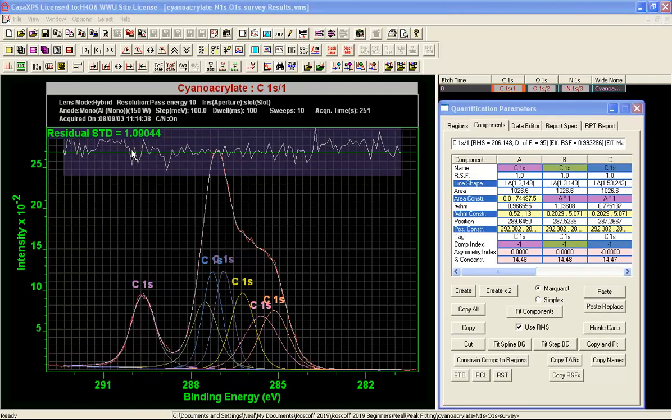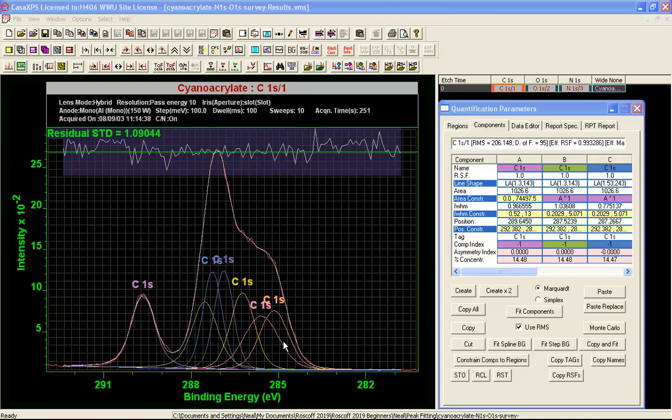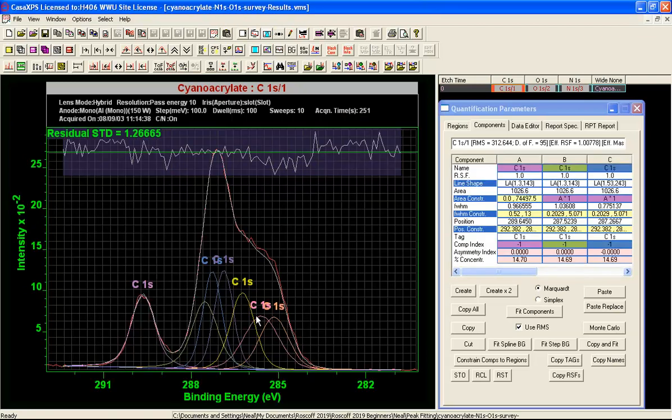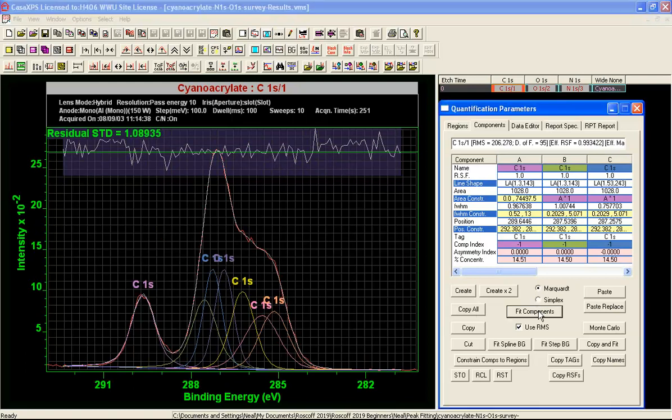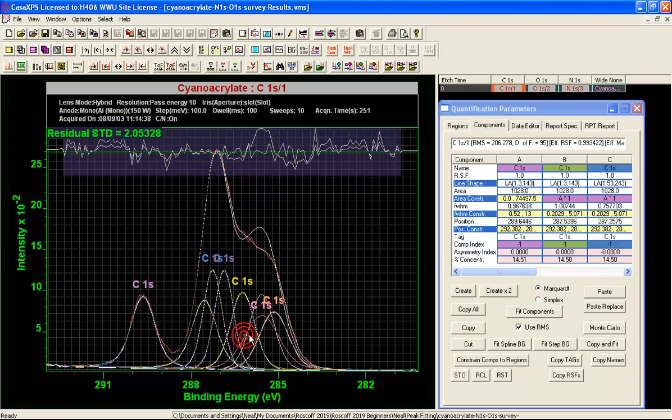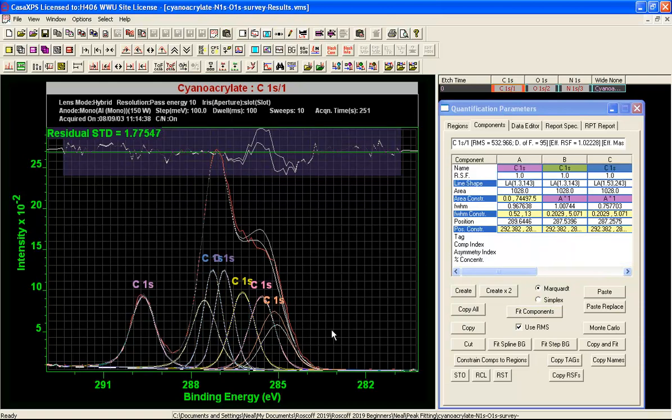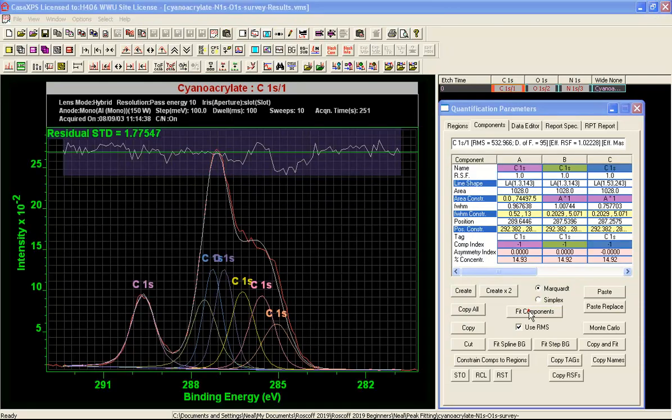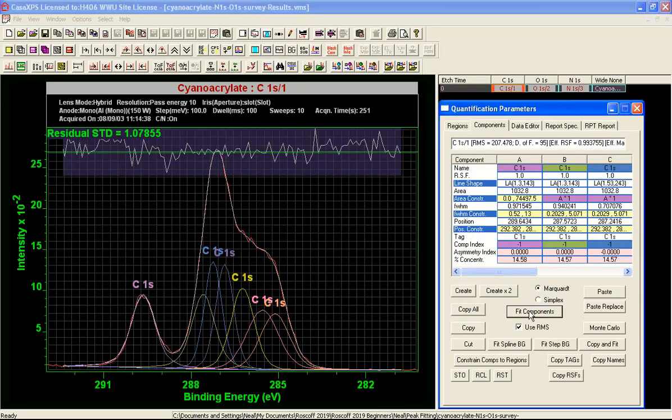That suggests that we've got a decent fit to the data. Although we do have a good reproduction of the data using this synthetic envelope, it's not a guarantee that you actually have produced a meaningful peak model. The best chance of producing the peak model is to do a comparison to other material that are similar, such as what I was using from the Beamson and Briggs database to make an assertion about these two peaks, for example, related to the nitrogen. And then a pair of peaks here related to the oxygen. The others are less certain. We've got a different amount of this unknown material here.